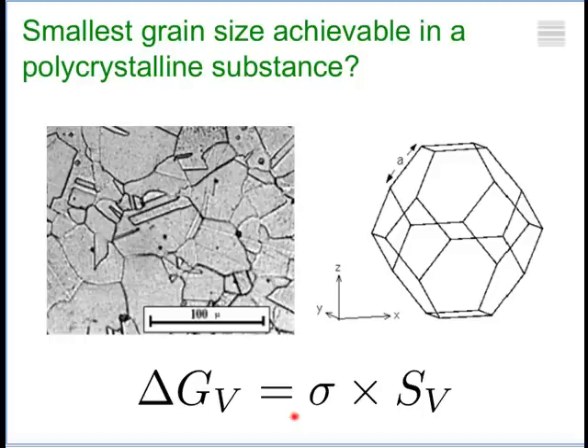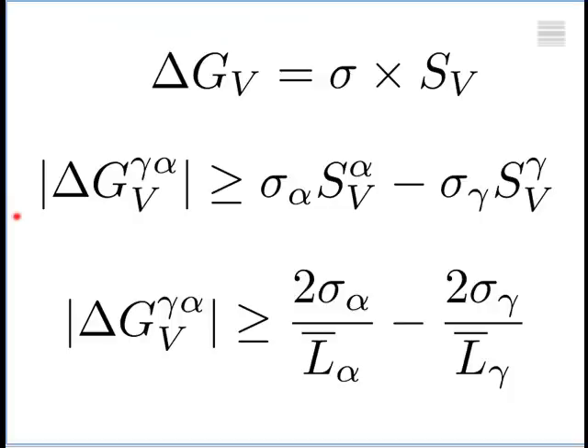Now, if you just remember this equation, that we are multiplying the energy per unit area by the amount of surface per unit volume, and we want to increase the amount of surface per unit volume. So if I just repeat that equation here, that is the cost. Where does that come from? Well, that comes from the free energy difference between austenite and ferrite. That is the driving force which causes austenite to decompose.